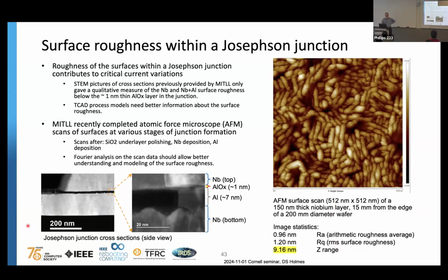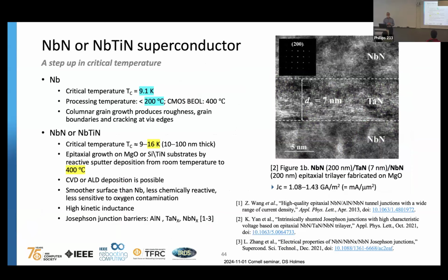I've just come to the conclusion that we're not going to take this to the finish line. We got to find something else. So people have been looking at other approaches: niobium nitride, niobium titanium nitride, and part of the group here at Cornell is looking at these and saying, well, there's some problems with niobium nitride. We really ought to focus, we think, on niobium titanium nitride. It's got some good benefits, higher critical temperature. We can use temperatures up to 400 degrees Celsius. That's not a problem. It has some challenges.